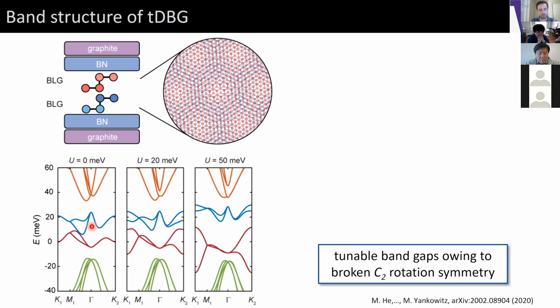When we start applying an electric field, we actually open an energy gap at the charge neutral point, so that isolates the valence and the conduction bands. But that comes at the expense of these gaps to the remote bands. So those will eventually close. And then as we apply an electric field, we can also tune the flatness of the conduction and valence bands. And that turns out to happen oppositely. So the conduction band gets flatter with the electric field and the valence band gets more dispersive. And again, this feature is not present in twisted bilayer graphene. It's really a consequence of the fact that we've broken this C2 rotation symmetry in the twisted double bilayer graphene lattice. So lowering the symmetry basically gives us more experimental knobs to play with.